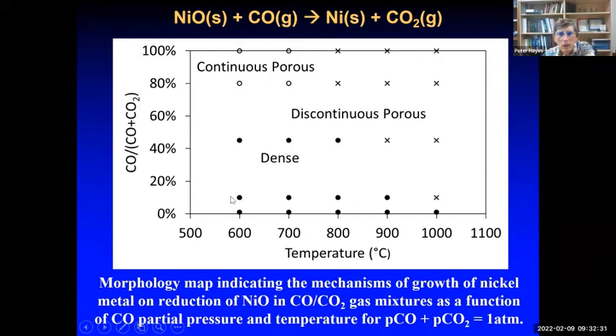We see that at the low thermodynamic driving forces and low temperatures, we tend to get dense layer of nickel forming. At high thermodynamic driving force, particularly at low temperature, we get a continuous porous microstructure. And at the higher temperatures and the lower driving forces, we tend to get this discontinuous pore growth.